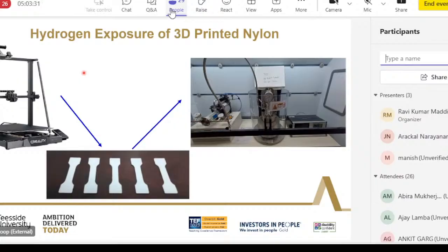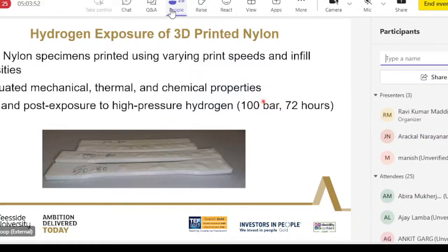As I mentioned, we have the Net Zero Industry Innovation Center, where we try to expose different materials. We have a reactor there, as you can see in the image. This reactor can be used for exposing different materials to a hydrogen environment. So you expose the materials to different hydrogen environments, then you can understand how the material behavior changes. And we could see that swelling has happened for 3D printed nylon.